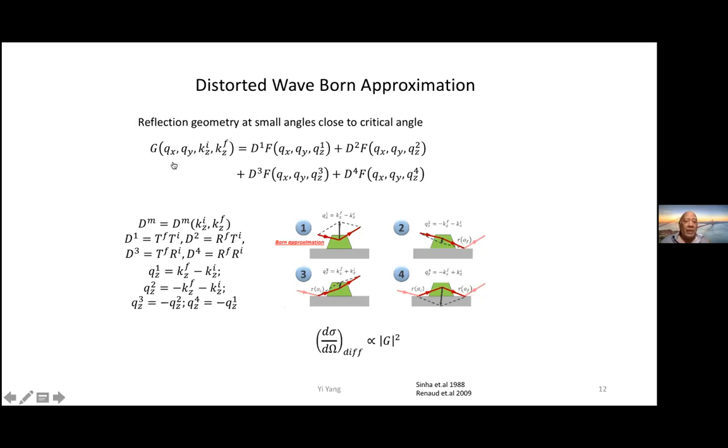And that's an interesting thing to note, because when you do a GISAXS experiment, you don't normally measure negative QZ because it's below the horizon. But if you do DWBA, if you do GISAXS, you'll see that those negative Qs are actually there and contributing. And the other thing is that if the things are two-dimensional, then the QZs don't matter. They're not part of the Fourier transform, and it goes back to the ordinary Born approximation. So 2 dimensions is trivial.